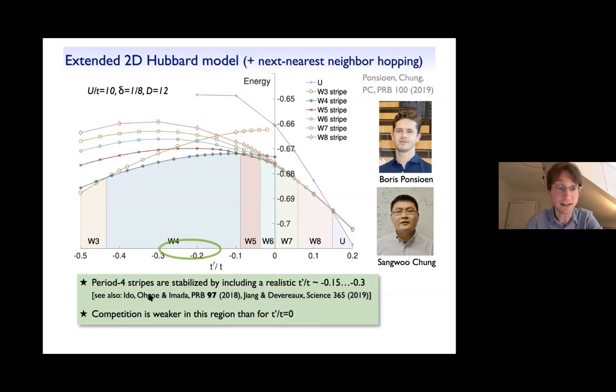So let me mention that a similar shift in stripe period has also been found in variational Monte Carlo simulations and also in DMRG simulations on width 4 cylinders. An interesting observation here is that the competition at finite t prime, so in this region here, is weaker than for t prime equals 0. So from that viewpoint, the extended 2D Hubbard model is actually easier to study than the plain 2D Hubbard model, where all these states are much more closely competing.